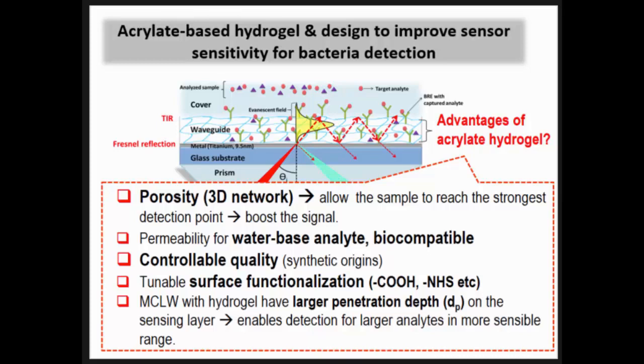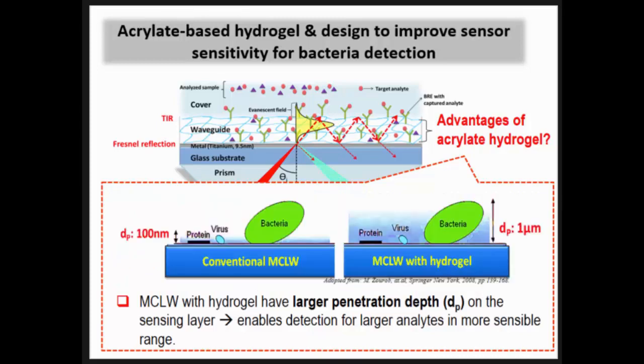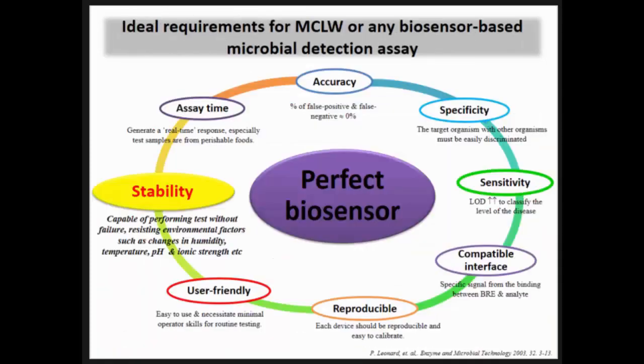We also can control the concentration, how much we want to load to the surface for the recognition species. This 4-layer structure with the waveguide using a hydrogel layer can also increase the depth of penetration compared to the conventional structure. Therefore, it's very suitable for the detection of larger analytes such as bacteria in a more sensible range.